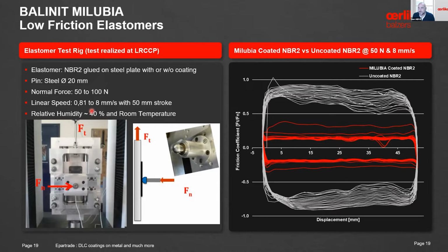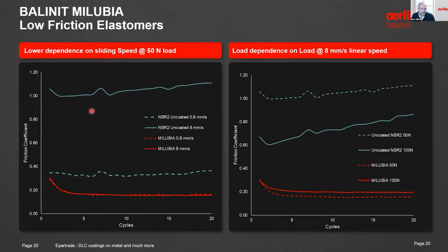So we came back to the office, we worked on our tribometer, and we replicated exactly the same thing that we saw before. So we could see that without the coating, we had a friction coefficient around 1. And with the Milubia coating, we were below 0.2. And from our point of view, it's a massive improvement. So we were able to reproduce, in the lab, a very low friction on an elastomer. And for us, that was a big step forward. But that was only the first step.